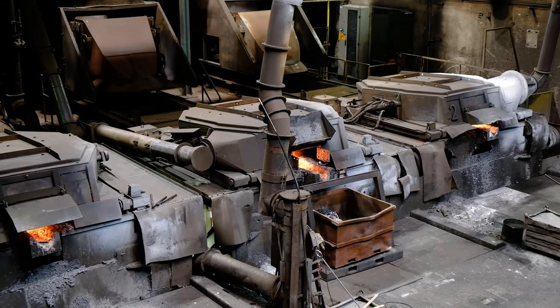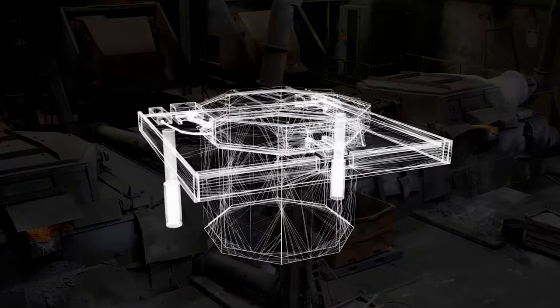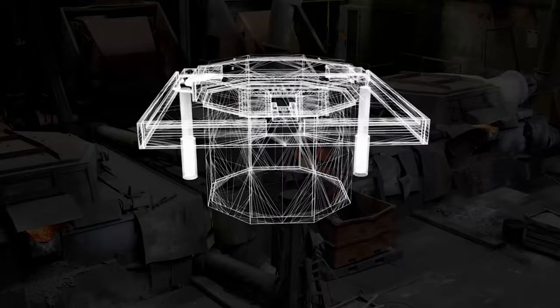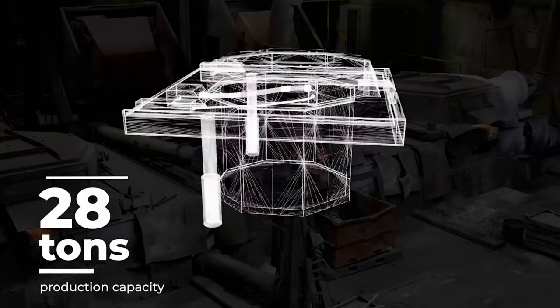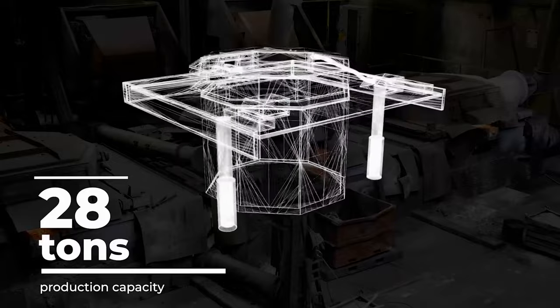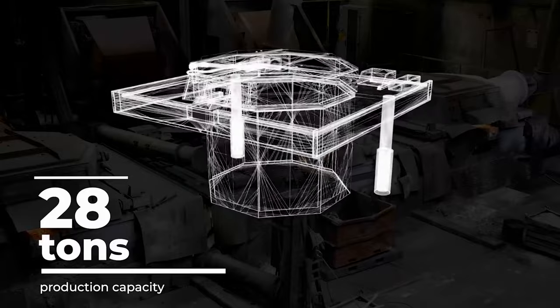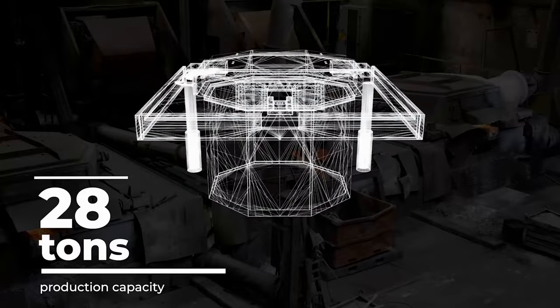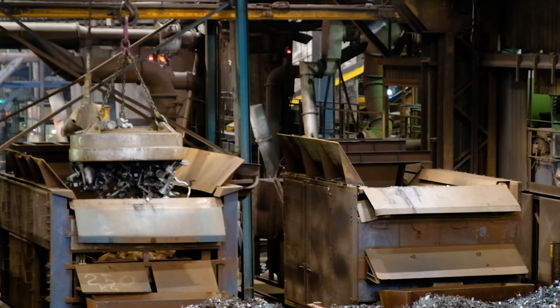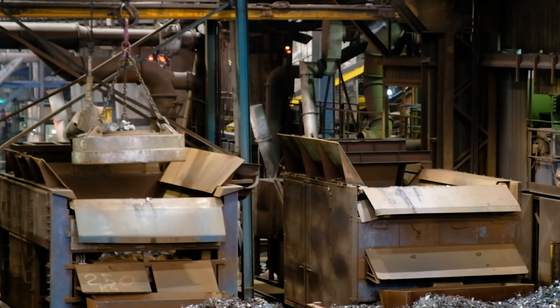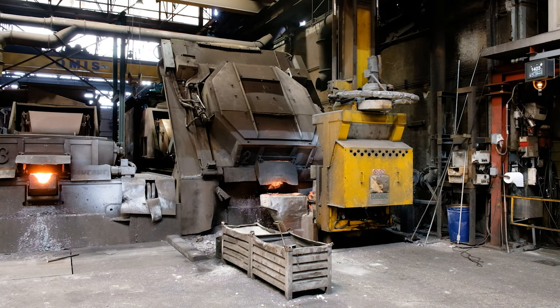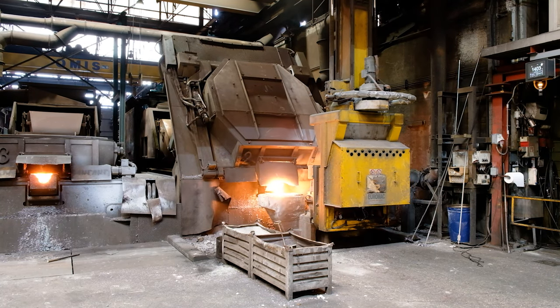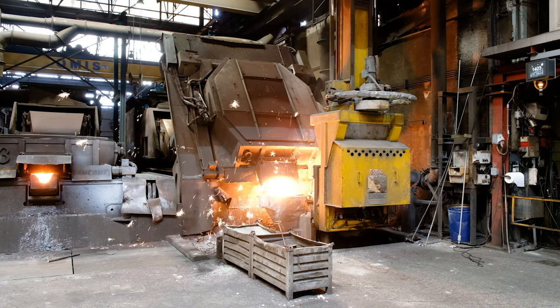Zanardi Foundry plant has three electric induction melting furnaces operating at mains frequency with a capacity of about 28 tons and an installed power of 3,300 kilowatts each. The ovens are loaded by vibrating loading platforms located in the rear part, while the liquid basic pig iron is poured in from the front part of the oven which has been previously tipped.